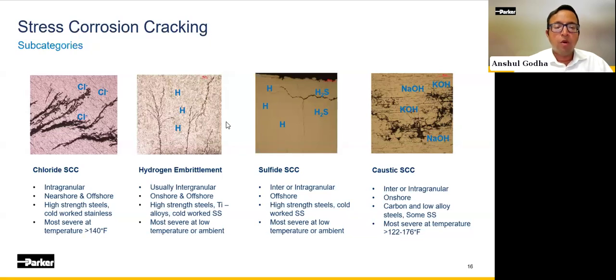Another big hint can be where the application was installed. Was it near shore or offshore, or maybe in a hydrogen-rich environment? Yet another big clue is what material has undergone the cracking. Is it a stainless steel? Is it a high-strength steel? Is it some other alloy? All of those show propensity to develop stress corrosion cracking using different mechanisms. And lastly, another big clue is the temperature at which the corrosion is occurring. So all together, one thing that is common with all forms of stress corrosion cracking is that you will always see branched cracking. That is probably the biggest clue that one can have as an end user to detect that we have a stress cracking or a hydrogen embrittlement issue.